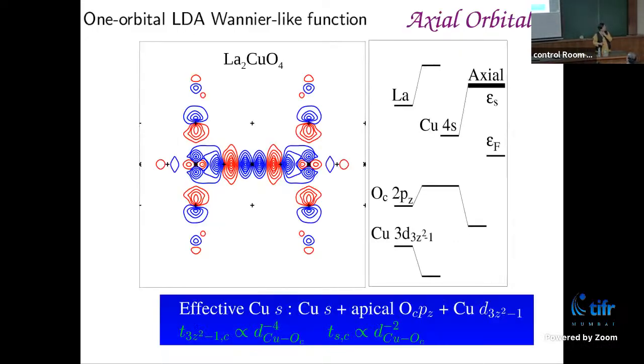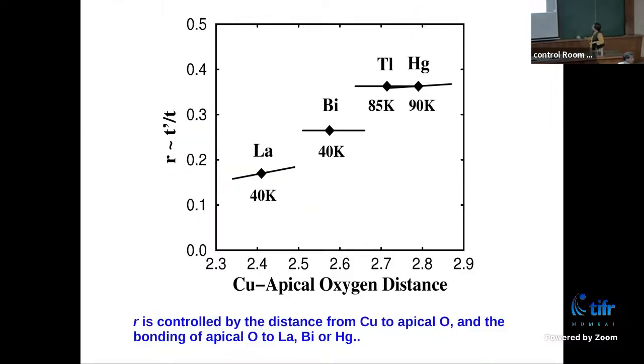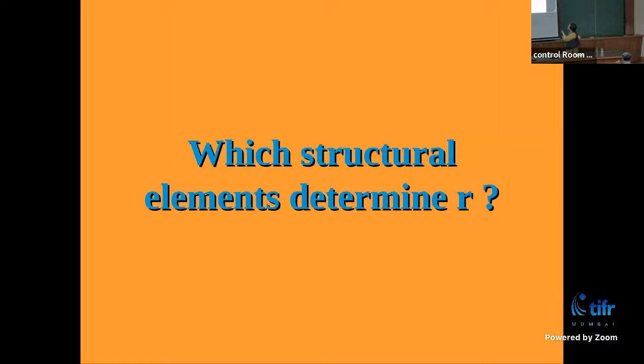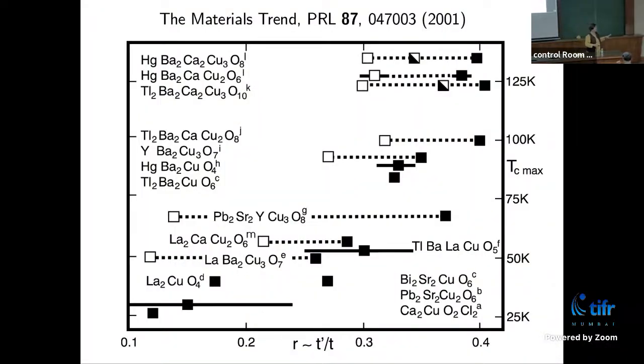Since these are all oxygen doped, that could mean the disorder effects are... No, these are all undoped. Our calculation of the R parameter is just for the undoped compound. But the superconductivity happens at finite doping. So what I'm saying is that the undoped material already has the signature. If you optimally dope, what will be the TC trend? You are saying that the larger the R, the higher the apical oxygen is. I'll come to that. Exactly, that is the thing. When they are farther away, the less effect they have by Coulomb's law. Absolutely.